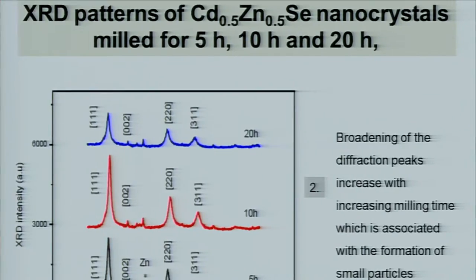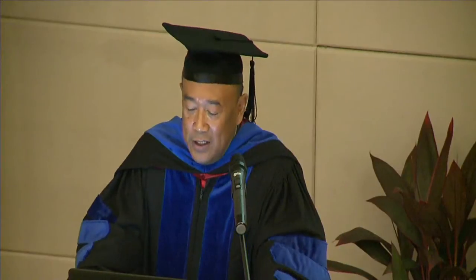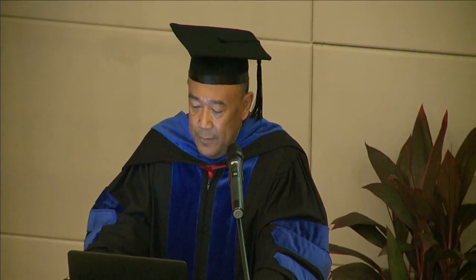However, there is a broadening in the peak from 5 hours, 10 hours, and 20 hours. So again, this broadening of the peak is not a bad thing, because it indicates to us that the particles become smaller. So when particles become smaller, it has this effect of broadening the peak. And it's true enough, if we